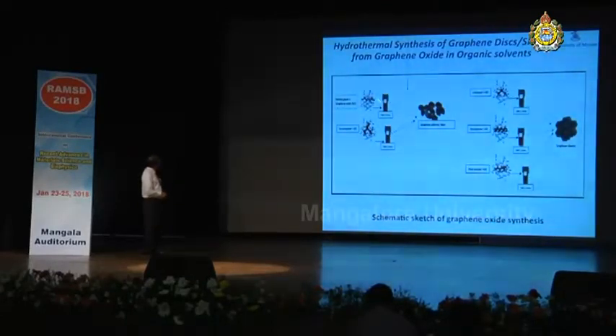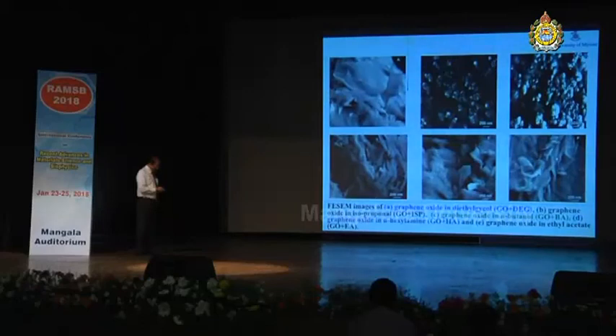Now the last part of my talk is on the graphene, reduced graphene oxide, the synthesis of it. This is a hot topic again. Graphene with some metal sulfides and oxides as composites give very special properties, and these are some of the FESEM images of graphene oxide obtained with diethylene glycol and graphene oxide in isopropanol and n-butanol. With variation in the organics, we have obtained different